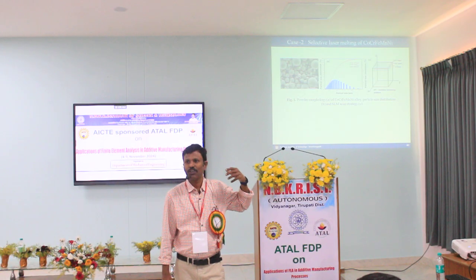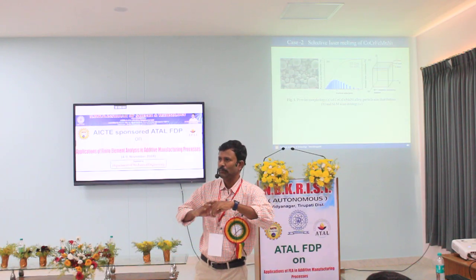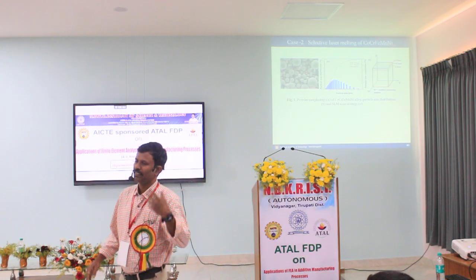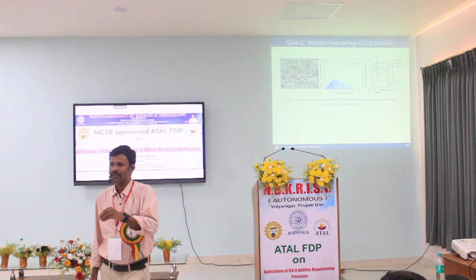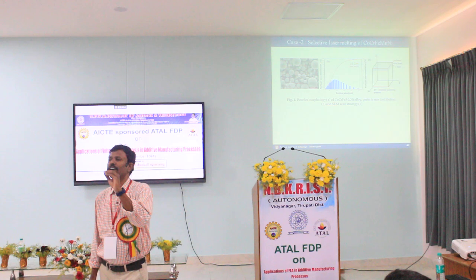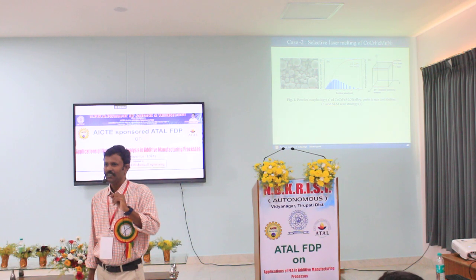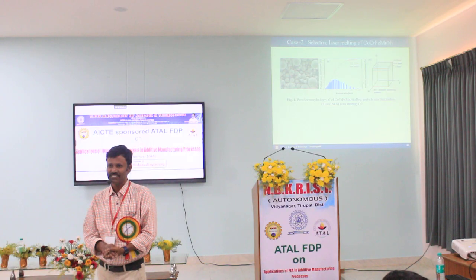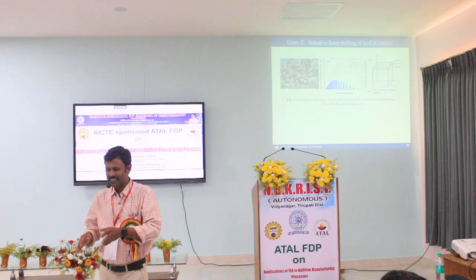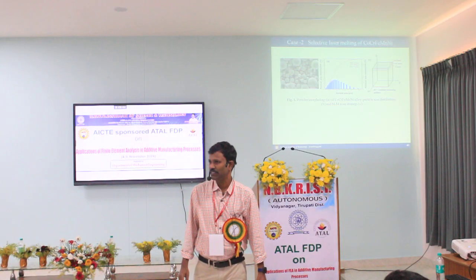Such a cocktail material, building it by selective laser melting became a very big challenge. We built it in Estonia, in Europe, in one of my friends' labs. For optimizing these parameters, it took almost 1.5 years. When depositing itself, cracks used to come at the back side. At the first level, when we were depositing, it used to split. A hell of a lot of problems we have faced.